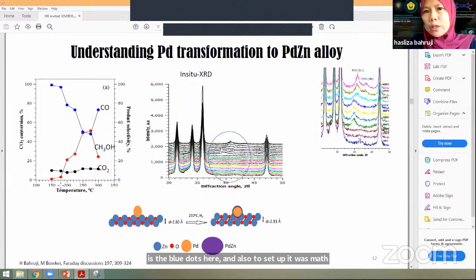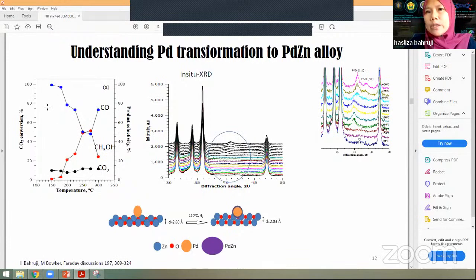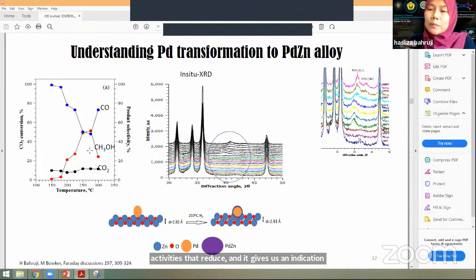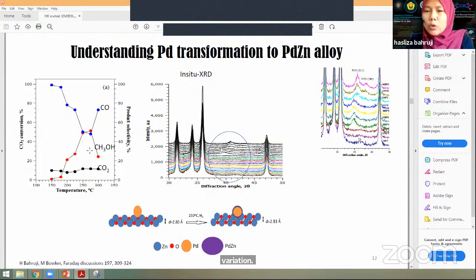So what we see, interestingly, is that the CO2 conversion is quite similar from 150 up to 350 degrees Celsius. But the selectivity varies greatly. At the very beginning, the catalyst is very active toward carbon monoxide production. This is because the catalyst itself is still palladium nanoparticles, not palladium zinc alloy. But when we slowly increase the temperature up to 250, we start to see that methanol is developing, and at the same time, CO selectivity starts to reduce. It gives us indication that the alloying process occurs at the same time as the reaction progresses, slowly transforming palladium nanoparticles into palladium zinc alloy.